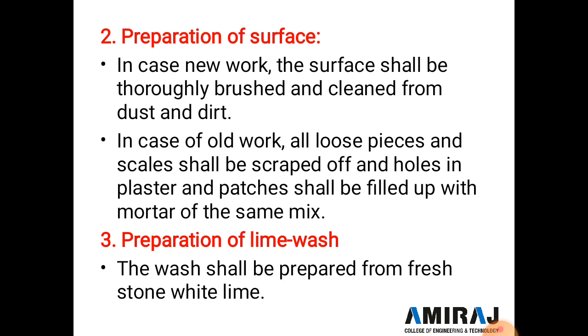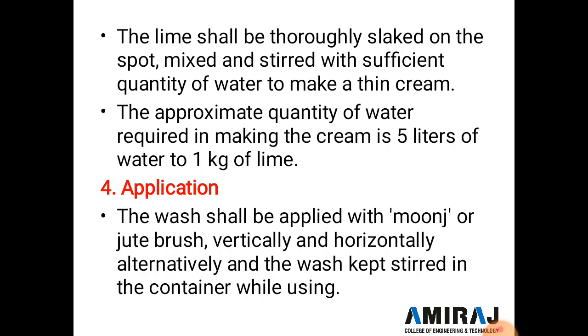And the third specification for the whitewashing is the preparation of lime wash. The wash shall be prepared from fresh stone lime, and the lime shall be thoroughly slaked on the spot, mixed and stirred with a sufficient quantity of water to make a thin cream. The approximate quantity of water required for making the cream is 5 liters of water to 1 kg of lime.